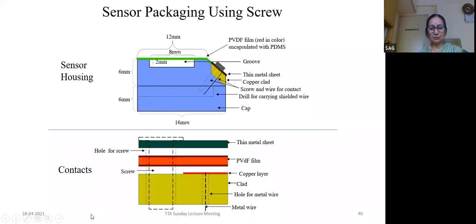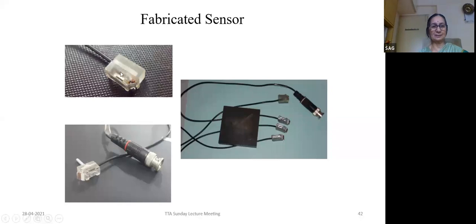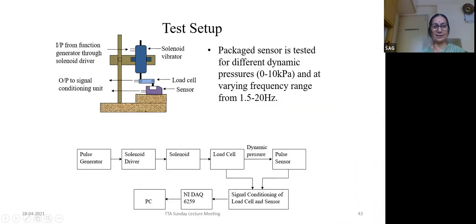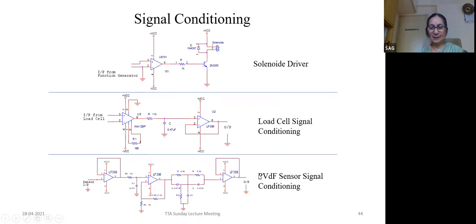Then we packaged it. This was the sensor which was fabricated, finally a packaged and usable sensor. We made such 3 sensors because at 3 pulse points, Vata, Pitta and Kapha, it was required. We tested them as load sensors for their characteristics. Then we developed a PVDF sensor signal conditioning circuit, because especially we required a 50 hertz rejection filter. That is required because our body is having 50 hertz input from the electrical wires which are going above us, or electrical field, and that is to be rejected because we are keeping in contact with our sensor.